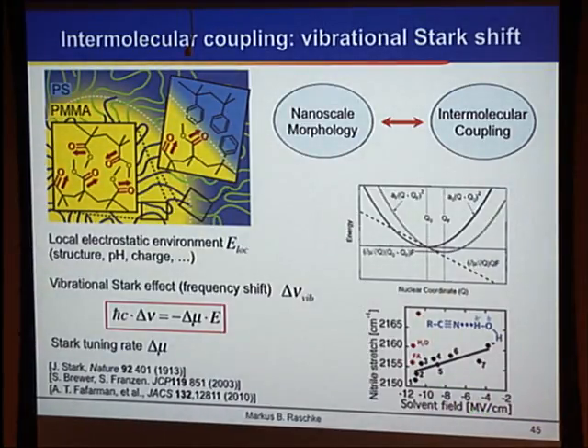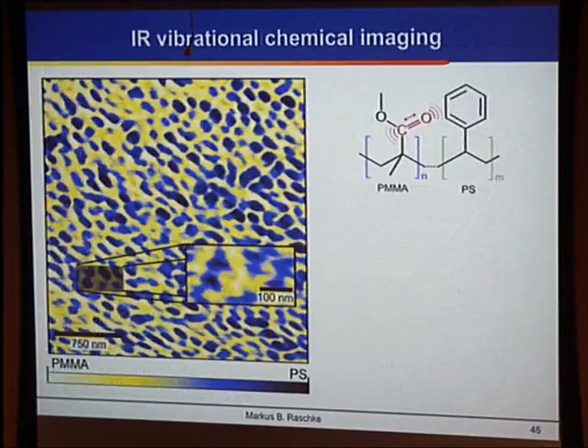So the fields between molecules are actually huge. If you've never really thought about it, it's megavolts per centimeter, which really affect that nuclear intermolecular potential. And so then from that spectral shift, you can calibrate it back and get this solvent field, in this case actually in a condensed phase system.